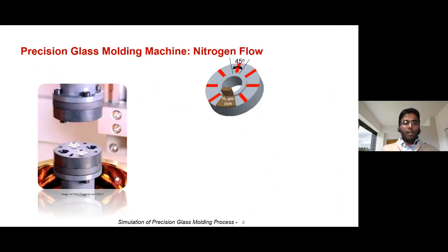Now, if you look at the precision glass molding machine, this is how the molding machine looks. You have the nitrogen gas flow, which blows nitrogen gas into the machine, and then you have a cooling plate in between, and then you have the mold inserts. And here you see the two glass preforms being placed on the molds, and you have the mirror surface finish molds over here. When you are doing the pressing operation, this whole assembly comes down, and then the chamber is closed.